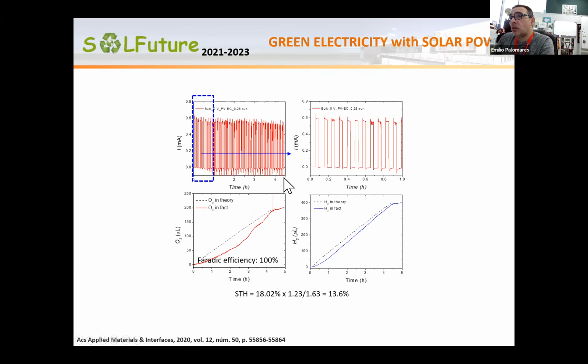We ran the experiment for more than 10 hours. Here is only about 5 hours, and it's really, really stable. So we got at that time a solar-to-hydrogen efficiency of about 13.6%. At that time it was the record.